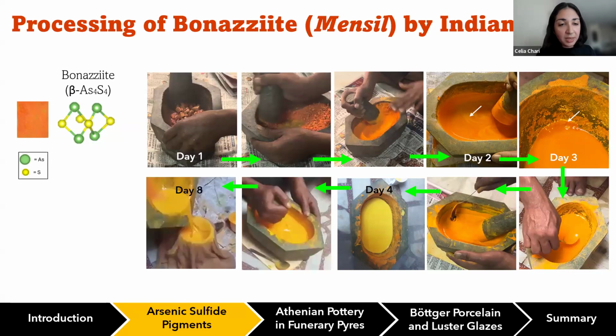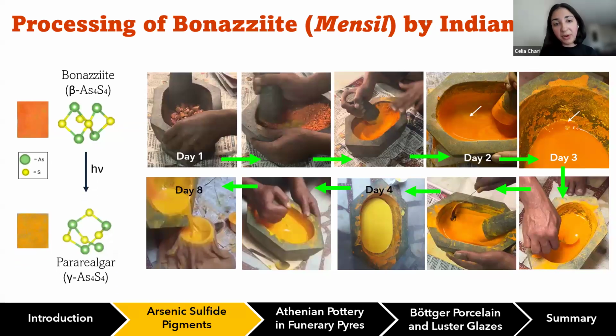And as the days go on and a week passes, you can see that the ultimate pigment that he makes is yellow in color. And when I analyzed that final pigment and compared it to the original bonazziite, I could see that there were considerable amounts of para-realgar within this final paint mixture. So I think this explains why, as a paint choice, Mr. Marotia did not notice that this pigment changed color that much after being applied onto paint. It's because without even knowing it, during the preparation process of this pigment and paint, he was inducing that photochemical reaction, making a paint that was a little bit more yellow, orange in color.